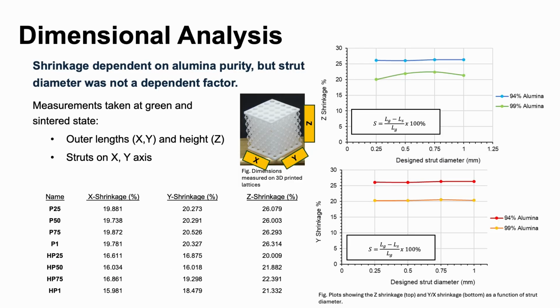So we calculated the shrinkage of the lattices after sintering for all lattice types. I measured the green X, Y, and Z lengths and tracked that same sample to measure the sintered lengths. So to calculate the shrinkage, I used the green length and subtracted the sintered length and divided it by the green length. For both alumina types, the Z shrinkage was found to be the largest compared to the XY dimensions, and when X and Y were analyzed, the 94% alumina had a higher shrinkage rate than the 99% alumina.